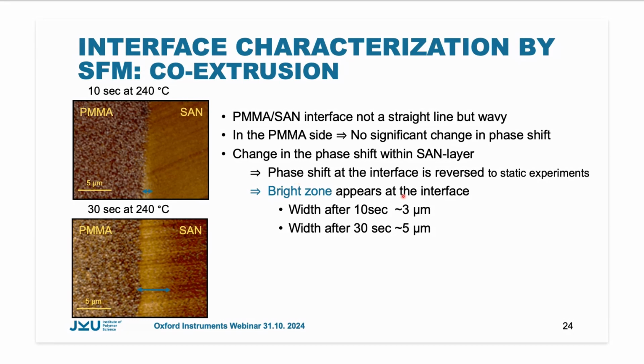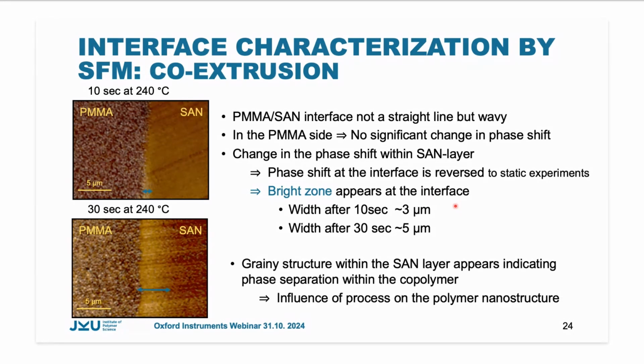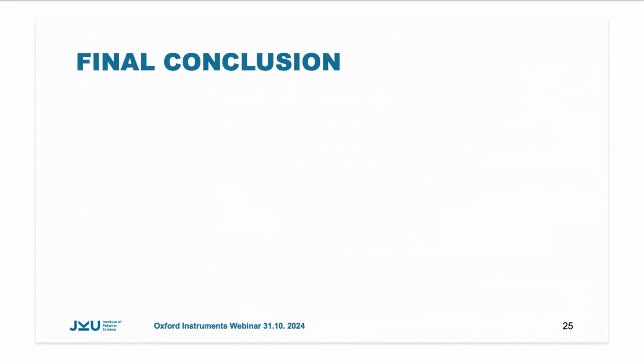And now a bright zone appears at the interface, which has a width about 3 to 5 micron, which cannot be really correlated to the interdiffusion of the PMMA. So this is one point which is still under investigation. What is also possible to see on the first glance is that within the SAN regime, a grainy structure appears, indicating that there is a phase separation within the copolymer, which will be caused mainly by the process conditions. With this, I can come to a final conclusion.